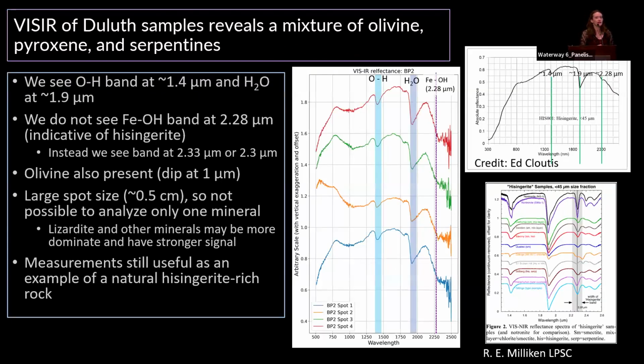So to start with the VISIR results, I've realized in these early stages of research that these samples are actually very heterogeneous. In my results, I had seen different signatures of different minerals, including magnesium-rich serpentine, olivine, and I see the OH bands at 1.4 and the H2O at 1.9, and bands at 2.33, which is the magnesium-rich serpentine, but actually no band right at 2.28. And so even though these are definitely hisingerite rich, they're a mixture of many different minerals. So this is an example of a hisingerite-rich sample. And this here from Milliken has a couple examples of even mixtures. And I think that is what we're experiencing here, mixtures between the iron-rich and the magnesium-rich serpentines.